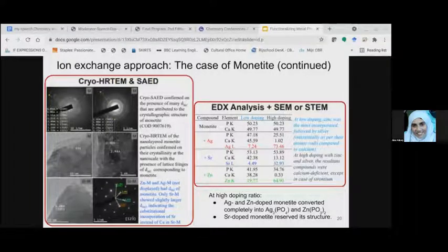And regarding the strontium-doped phases, I could find some expansion in their crystalline lattice, and this can be attributed to the substitution of the strontium ions in the places of calcium ions, since strontium has an atomic radius bigger than calcium.